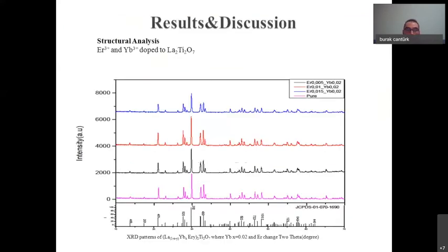So let's take a look at some of our results. In the compound of lanthanum titanate, due to the ionic radii being close to each other, ytterbium and erbium are co-activated inside of lanthanum. Also, we measured undoped phosphors and show the XRD diffraction in order to compare with the doped substances. As we can see from the graphs, the entire product samples display a single phase orthorhombic structure